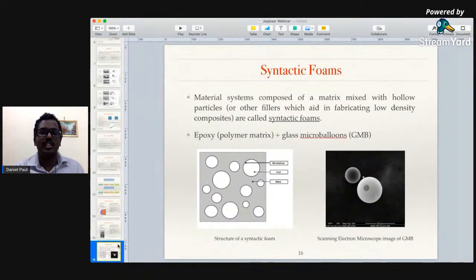While researching into these, we came across a particular material system called syntactic foams. Syntactic foams have a matrix, which can be polymer, metal, or any other matrix, in which we add some hollow particles or any other fillers or additives which aid in fabricating low density composites. As you can see in this image, in the structure of a syntactic foam, there is a matrix in which we add hollow particles. Inside these hollow particles, there are intentional voids. But these particles are strong enough. These are not just some sponge or something, but they are reinforced voids, which reduce the density and weight of the material extensively, at the same time giving considerable strength.